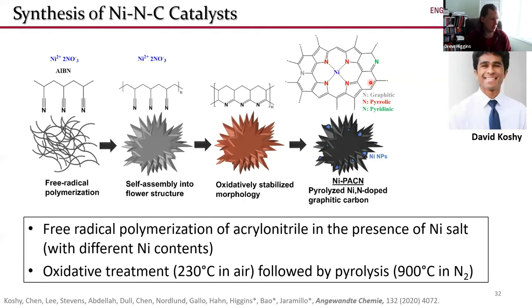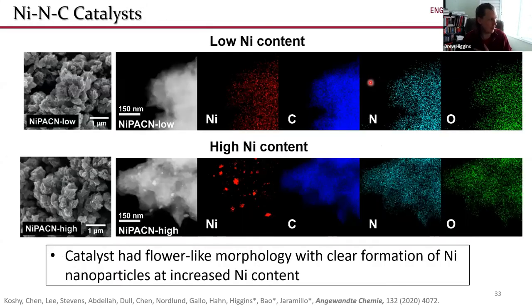So I had the pleasure of working with a very clever PhD student, David Koshy, and he developed a method for preparing these nickel nitrogen carbon catalysts in a fairly clean way. He polymerized acrylonitrile in the presence of nickel salt, and he heated them up, first doing an oxidative heat treatment, followed by a pyrolysis at a high temperature in nitrogen. And he arrived at what he called these nickel nitrogen carbon nanoflowers.